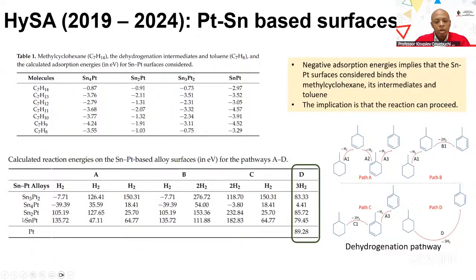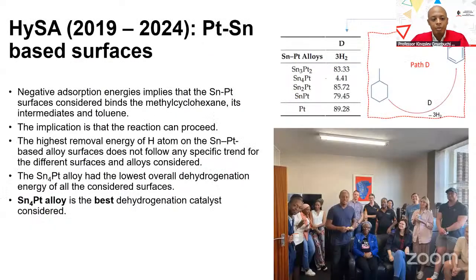Here we look at the overall dehydrogenation energies, and we see that our tin-based Sn4Pt actually resulted in significant improvement in the overall dehydrogenation energy. Actually, there's a significant drop. An important implication is that this can be a good catalyst for this kind of reaction.